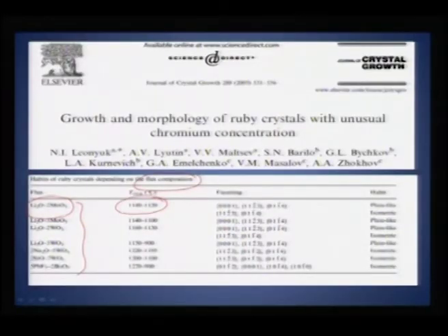And this lithium oxide molybdenum oxide is actually water soluble. Therefore, when the crystals are formed, all you need to do is just dump it in a hot water, then all these things gets dissolved into water, and what is remaining as a residue is nothing but the crystals that are formed. So, this is a simple protocol of a flux method.